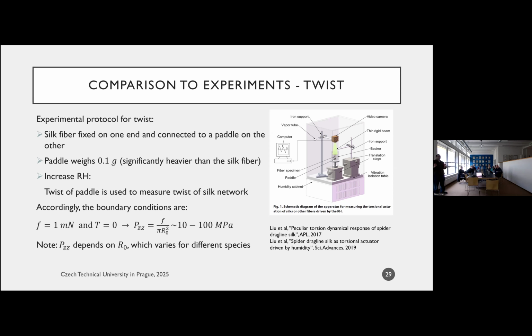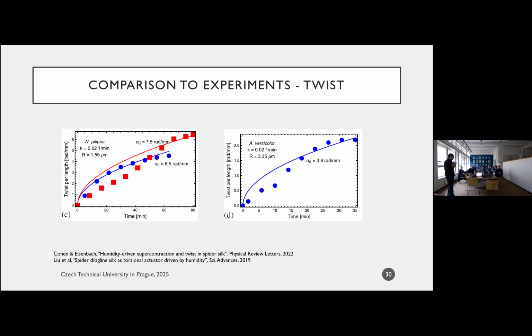And so once we had this, we said, okay, now we understand what's going on. Let's compare. And so we compared it to the experimental findings. What you see here is the twist per unit length as a function of time for the different fibers that we took, right? So these are 2 different fibers. We can see that the model captures the overall trend. This is a bit of a mishap, which I still don't understand why this happens, but overall the trends we're capturing here, we fit the trend pretty well. And when we submitted this to PRL, we submitted just like this.